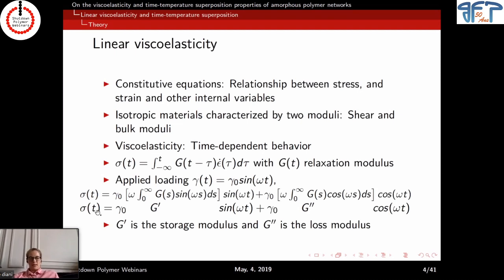And this stress can be defined with one part that is in phase with the applied strain and one part that is in anti-phase with the applied strain. So the first one defines G prime, the storage modulus, and the second G double prime, the loss modulus. What's interesting here already, you can see that G prime and G double prime are not independent. They're both defined by the same function, the relaxation modulus.